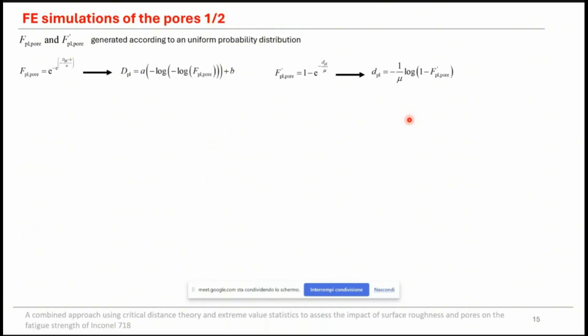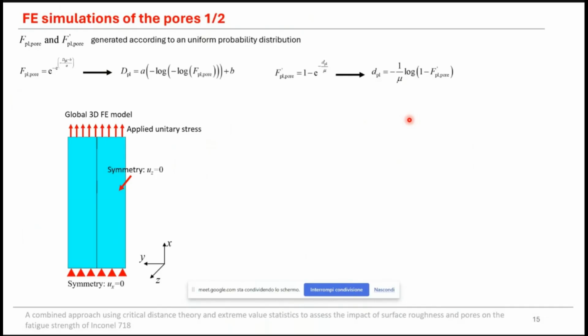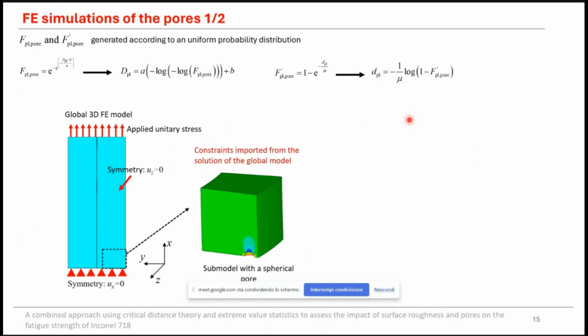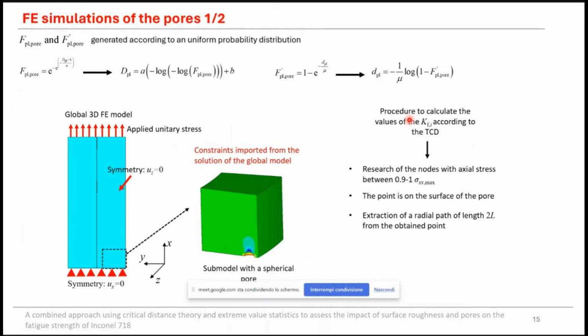As a consequence, we obtained two data sets of pore diameters and distances from external surface that were used in 3D finite element simulations with some modeling technique. And once the finite element simulations were completed, we identified the nodes experiencing axial stress sigma XX ranging between 90% and the maximum. We extracted radial paths and calculated fatigue stress concentration factors according to the line method and point method. Clearly, the node experiencing the highest fatigue stress concentration factor was the selected one, and we repeated the procedure for the other pores.